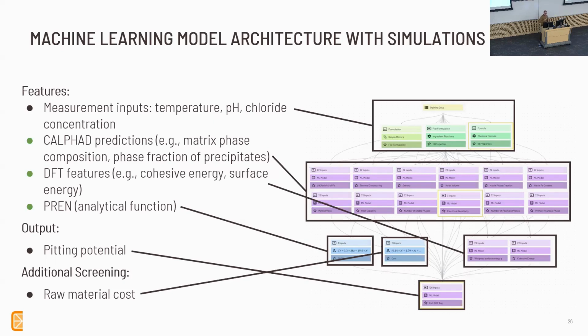So things like, what is the matrix phase? What is the composition of the matrix phase? Are there precipitates? If so, what percentage of the microstructure is made up of precipitates? Things like that. We also integrated DFT, which is an atomistic quantum mechanical-based system of simulating properties. In this case, things like surface energy, cohesive energy, band gap was on here. And then we also looked at PREN, which is a very simple rule of thumb kind of model for corrosion engineering that a lot of engineers use out in the field.